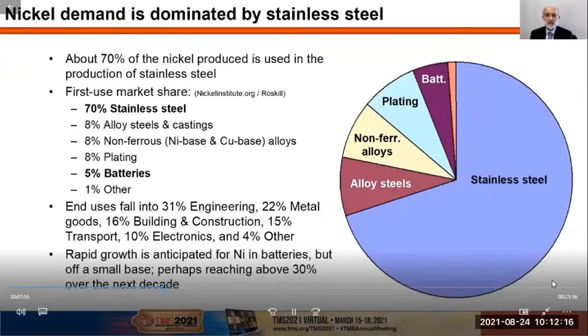Nickel demand is dominated by stainless steel, which accounts for about 70% of the first use market share. There is 8% that goes to alloy steels and castings, another 8% to non-ferrous or nickel-based or copper-based alloys, 8% to plating, and 5% to batteries, of which we'll talk more later. We can also classify the distribution by end use into 31% engineering, 22% metal goods, with the remainder going to building and construction, transport, electronics, etc. Rapid growth is anticipated for nickel in batteries, but off a small base, perhaps reaching over 30% over the next decade.